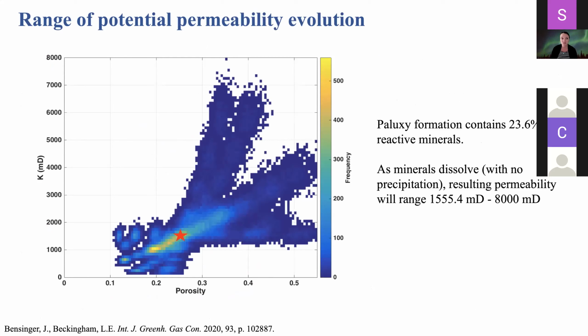So this is a potential CO2 storage site. And some of the things we want to know is that once reactions start occurring after you inject CO2, like we saw in the first system, and you have changes in the porosity that are due to mineral dissolution or precipitation, what's going to happen to the permeability? So the initial permeability of the site is shown here as this red star. And we know from our earlier simulations, the fraction of reactive minerals in this site is 23.6%. Now those are not all going to react right away like you saw in the simulations, and maybe only a fraction, or some of them are going to be pretty slow. But as those minerals start to dissolve, what's going to happen to permeability?